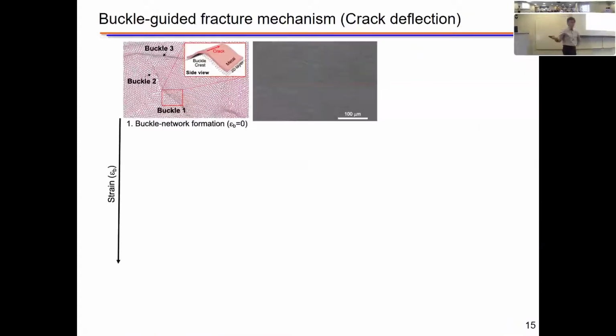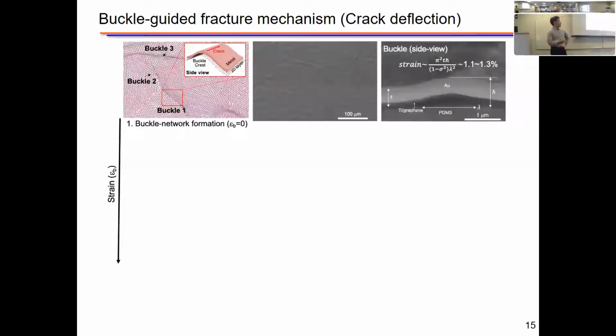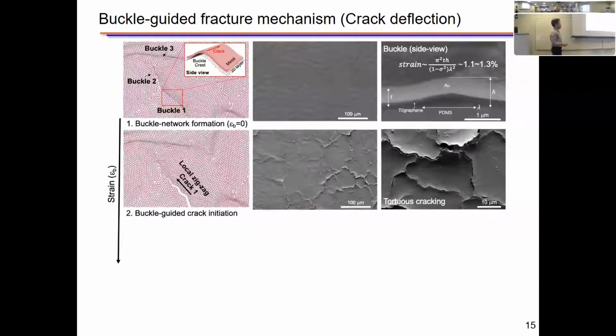So directly jumping onto the mechanism part, which we call the buckle-guided fracture mechanism. As step one, after the metal deposition, we saw a heterogeneous buckle network formed on the surface. By looking at the cross-section, we're able to estimate the accumulated strain of the crest of the buckle, which is around 1.1 to 1.3%, indicating that the crests of the buckles are susceptible to initiating fracture compared to the non-buckled area. And that's what actually happens in the next step.